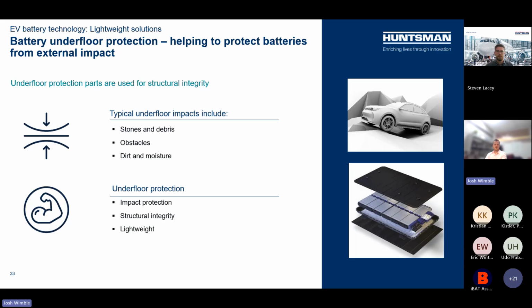You'll see these already with biaxial glass fiber composites, PU, and a sandwich with PU foam core or a long fiber injection, LFI, which is long fiber glass inside the polyurethane foam, in a number of vehicles on the market today. That high fiber content enables an excellent mechanical performance. Lightweighting is the key, so with pretty similar protection to what you get from maybe a steel sheet, you can see about 50 to 80% part weight reduction.